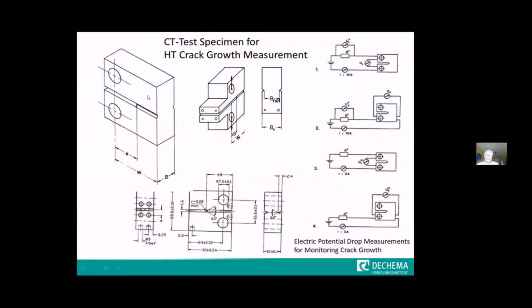So we have a modified compact tension specimen in this case. In some cases, we even had this modification here, which made it easier to weld the measurement wires to the specimen. What we measure by the potential drop technique is that we send some current through the specimen, which comes out on the other side again. Depending on the remaining cross-section after crack growth or during crack growth, you get a signal which you can measure. With this signal, if you calibrate it, you can measure the crack growth rate, even at high temperatures in aggressive environments for such kind of specimen.